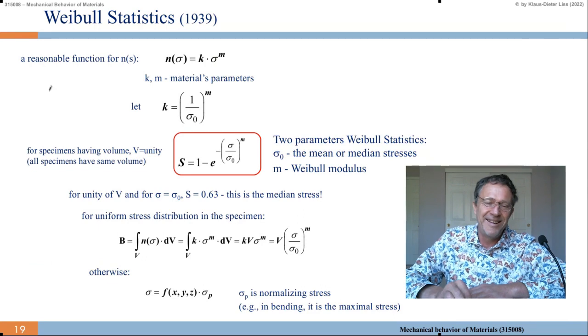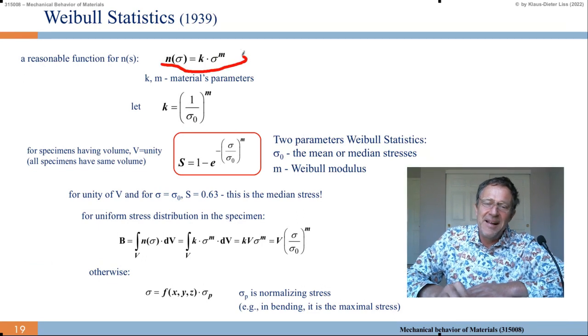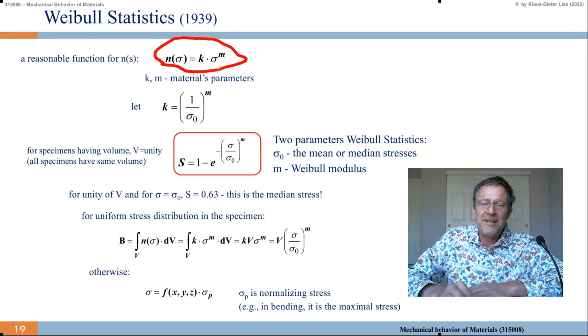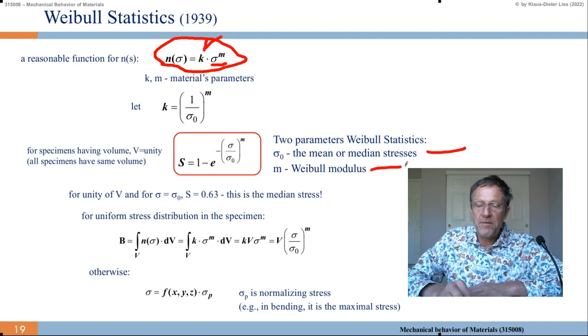And now again, always do the same. We say now n of sigma is a potential function of sigma again with a constant k. And let's say k is 1 over sigma 0 to the m. So for specimens having the volume V is unity, all specimens have the same volume, then the failure probability is 1 minus e to the minus sigma over sigma 0 to the m. So we have two parameters in the Weibull statistics. We have the sigma 0, which is the mean or median stress, and we have the Weibull modulus m.